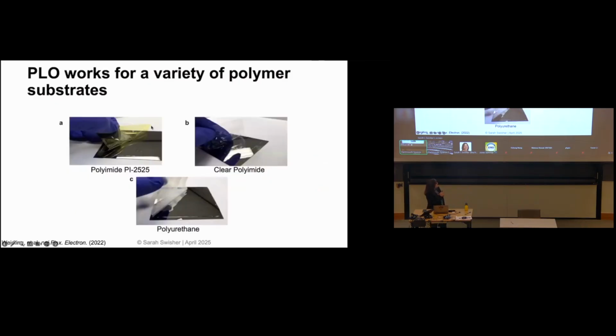And the other nice thing is because it doesn't rely on the polymer actually absorbing the light, all the light's getting absorbed in the metal. So what that means is it's sort of agnostic to what polymer you use. We can use polyimide or polyurethane, or this is a clear version of polyimide versus our normal sort of capped on orange looking stuff, right? And it doesn't matter whether or not the polymer absorbs this wavelength of the light because it's all getting absorbed in the metal. All you have to be able to do is reach that ablation temperature. And we can do that with multiple different polymers.